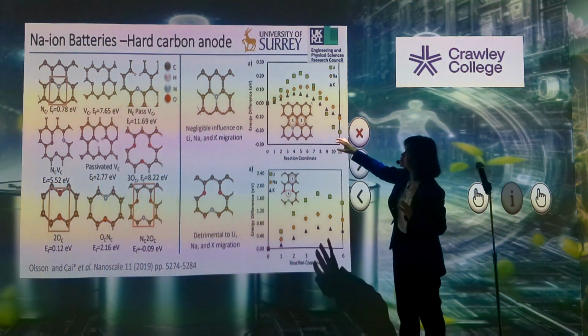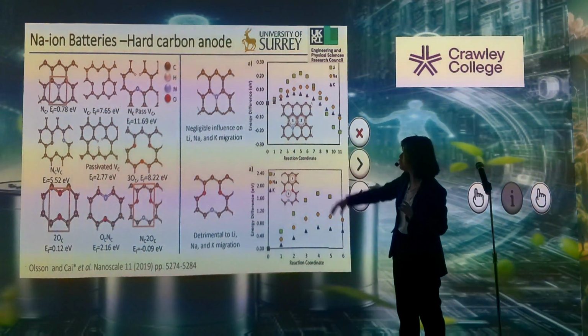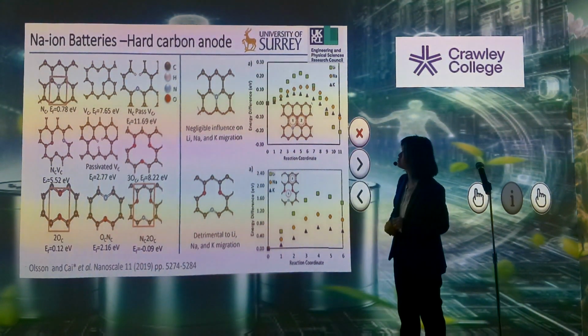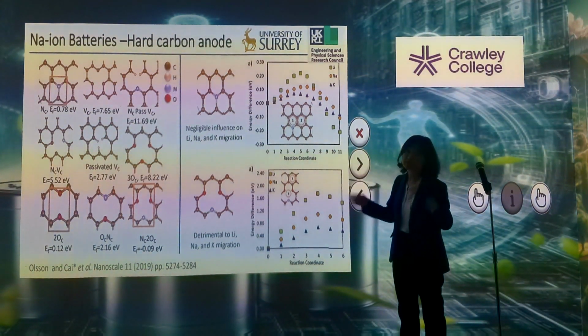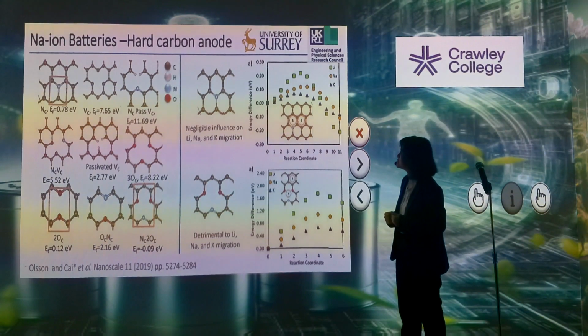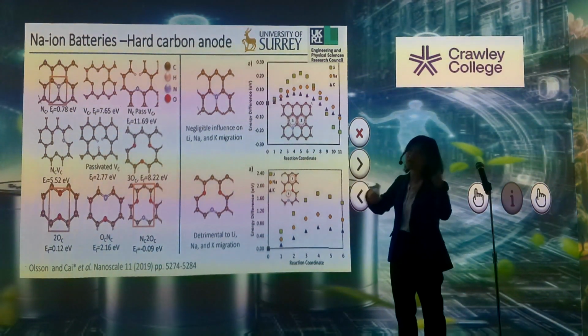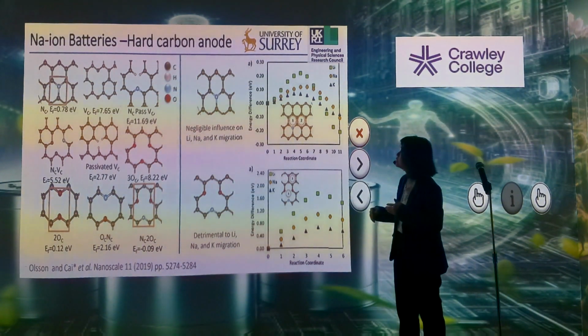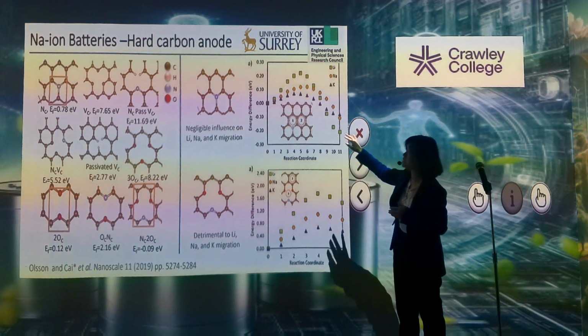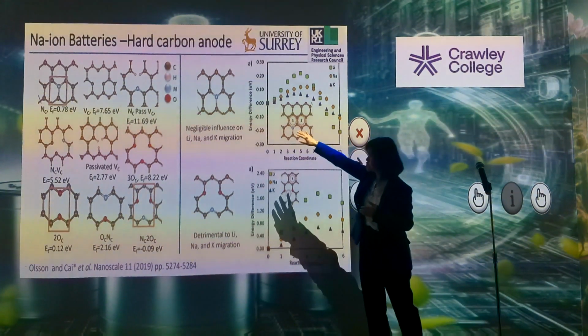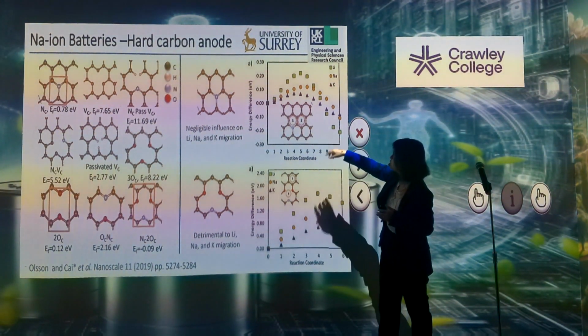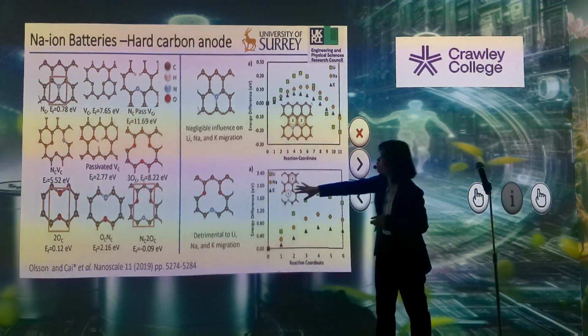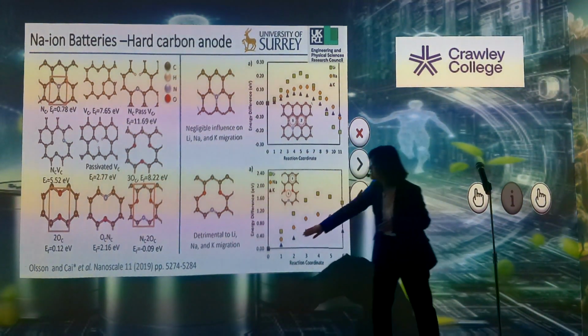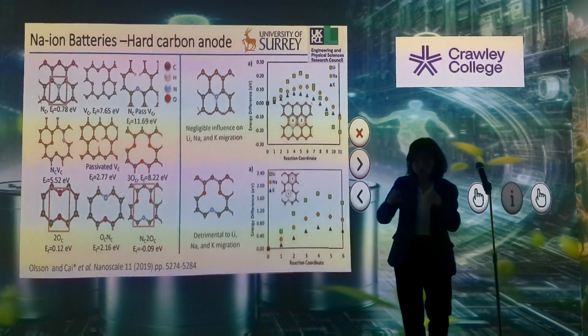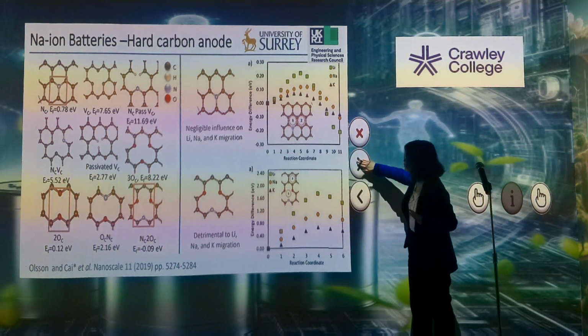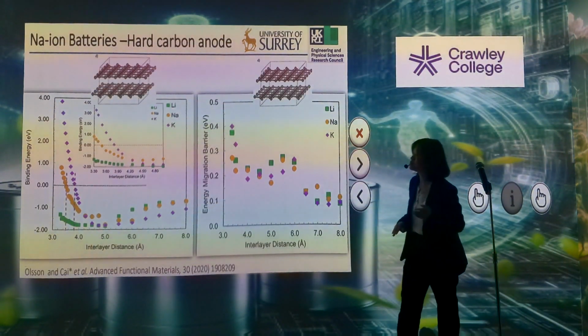And when we look at the absorption, we can see that they all provide stronger absorption of the ions, meaning that they will probably give higher storage capacity. But if we think about how ions move within the material, we don't want very high migration barrier. The nitrogen doped one doesn't have very high migration barrier, but the oxygen one creates a big migration barrier, meaning that the sodium ion could be trapped there, which is not good for the charge-discharge process. So we don't want a lot of oxygen there.